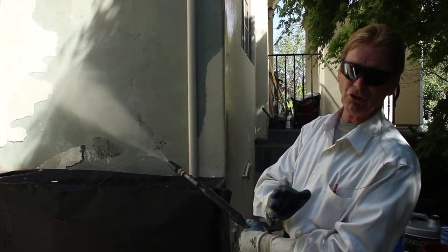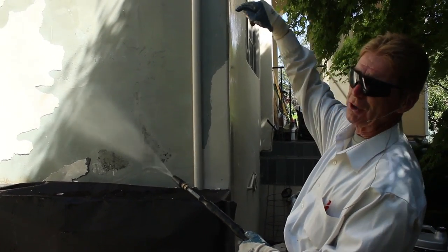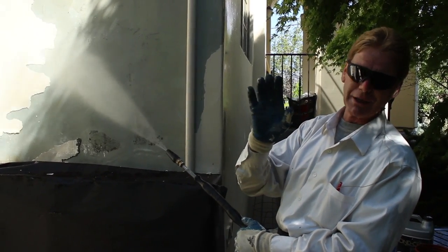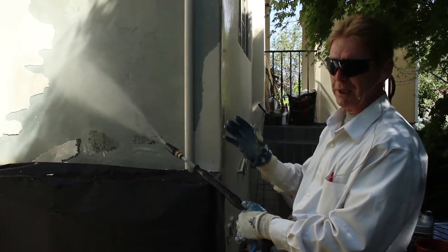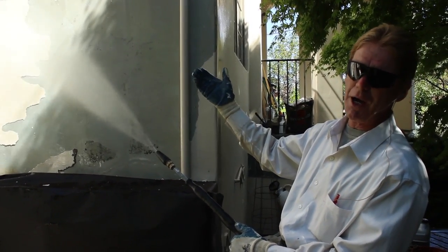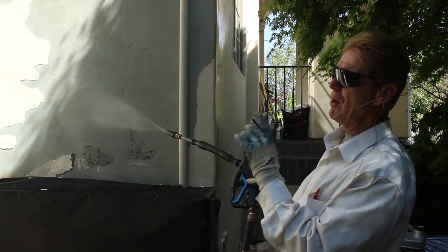There's a big issue of whether you should seal a house or have it be breathable - but that's not this video. The water went in on the top, comes down, and there's nowhere for it to go so it bubbles. Every year the cracks get bigger because of spalling - the water gets in, freezes, and pushes it out a little bit. That's what happened originally. Water shouldn't even get behind it, but that's another story too.